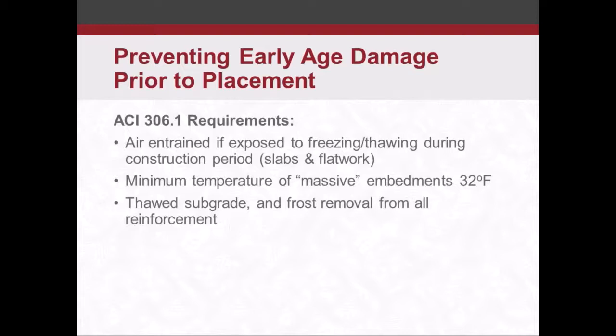So 306.1, again, these are the ACI specifications. They state that the concrete shall be air entrained if the concrete is exposed to freezing and thawing during the construction period. That's pretty important to know. So, this project I was talking about here in the Albany area, when they're doing construction in the wintertime, they may have an interior slab that they're placing that during its service life isn't going to see any kind of freeze-thaw cycles because it's inside. But if it's exposed to freezing and thawing during the construction period, it needs to be air entrained. If it's not air entrained, it's not going to hold up to those freeze-thaw cycles. That's something that is very often overlooked.